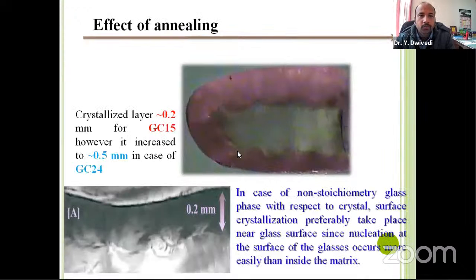When you keep the heating rate approximately 15 degrees Celsius per minute, crystallization actually starts near the surface. So there is surface crystallization, or bulk crystallization. In this case we keep this heating rate around 15 degrees Celsius per minute.